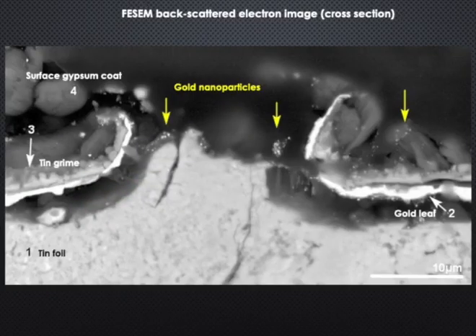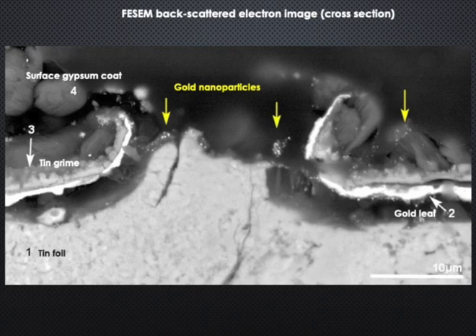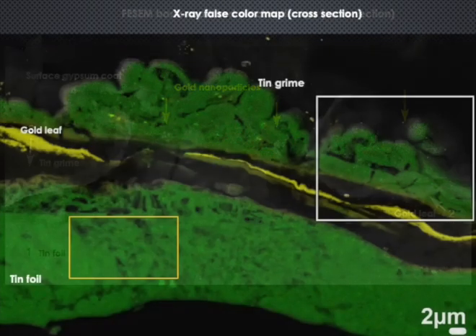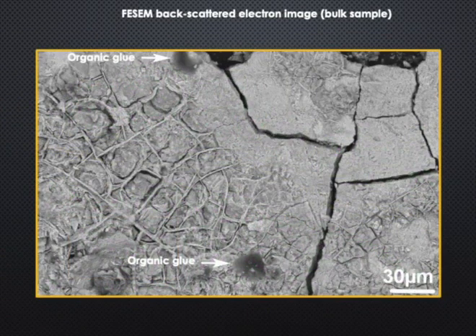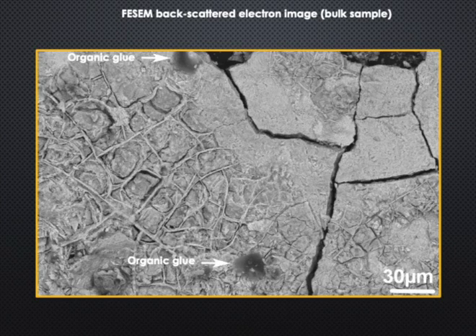Voids and fissures in the gold leaf are channels through which moisture reached the underlying tin foil. These channels provide an ionic pathway between the two metals, promoting microgalvanic cells. The severely degraded tin foil shows spongy bone-type texture in cross-section and cracked mud-type texture at the surface. The non-conductive organic film between the tin and the gold, which prevents their direct electrical contact, is almost lost. In the presence of moisture and chlorides, the tin foil degrades by galvanic corrosion.